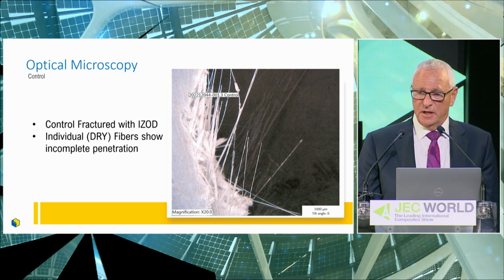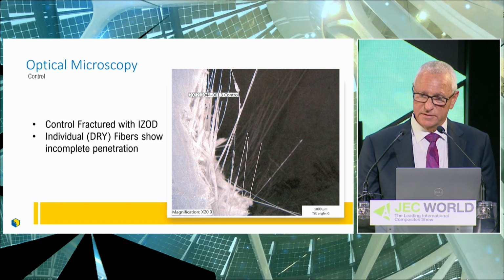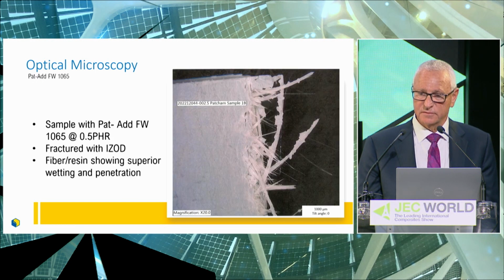So we had some friends at Pultrusion do some microscopy for us. Thanks for that. I should probably have put these on the same page, but this is the control, and you can see the single strands not all that well wetted out with resin. And then you can see this is the 0.5 parts per 100 of the 1065 on there, and you can clearly see the resin that's adhered to the fabric or to the fibers.